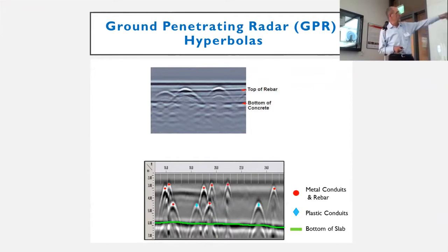Now, it's possible, we had plastic conduit, other materials too. So when it bounces off of that, it tells you where the location is. You can't tell when you're doing scanning. This is what you see. I'm just showing this to highlight what it's capable of. So you can't really tell what these peaks are. The only way you can tell, well, we use it primarily for locating post-tensioning cables. Because as you probably know, coring post-tension concrete and hitting the post-tension cable is a very expensive repair, $15,000 or whatever. So when you're scanning, that's what you see.